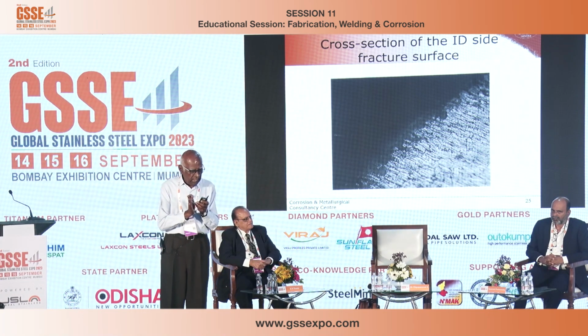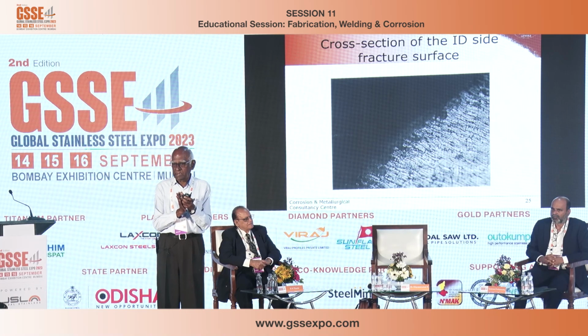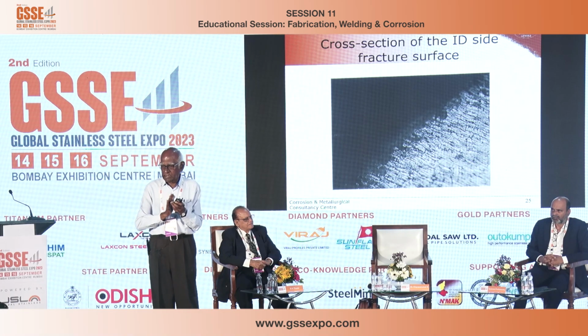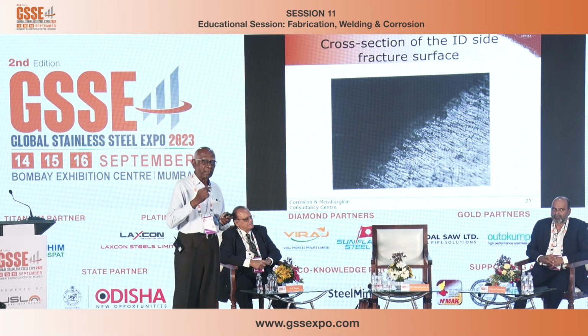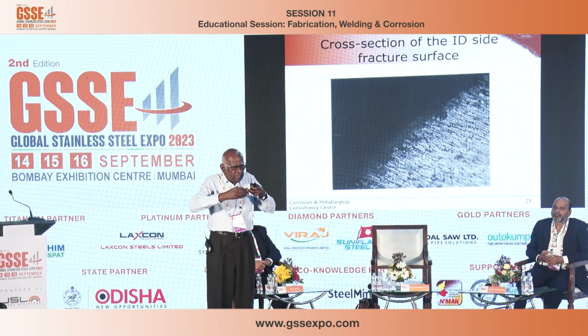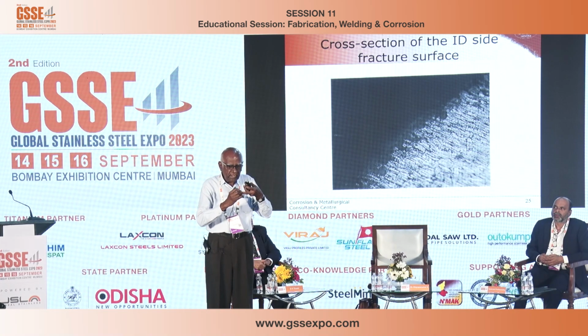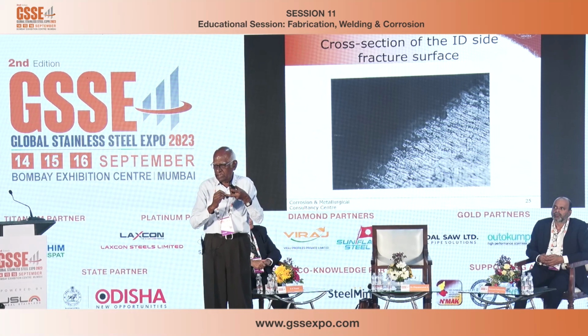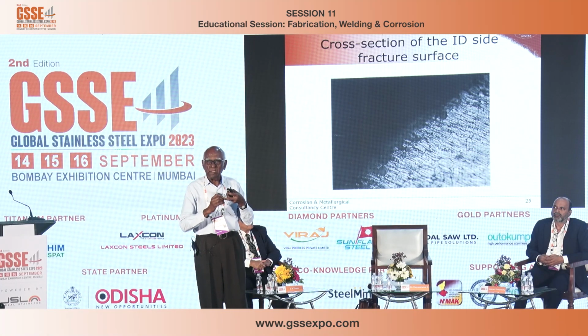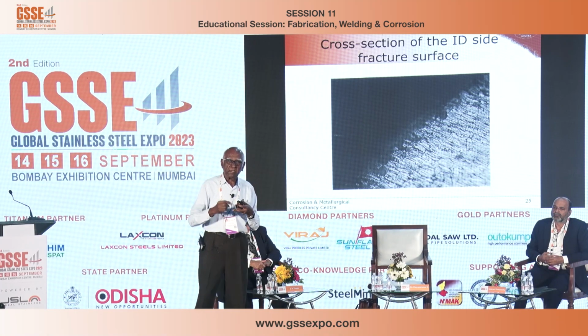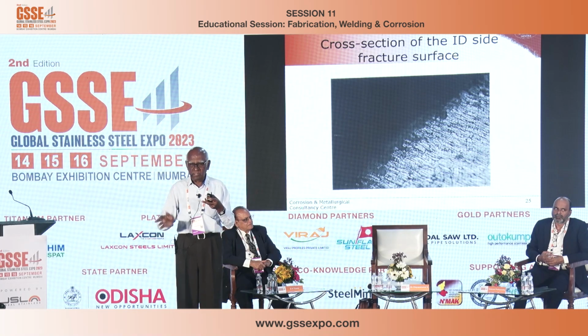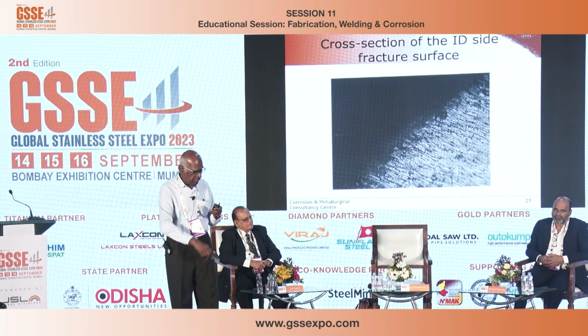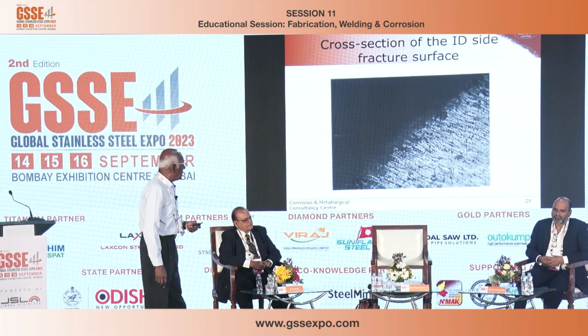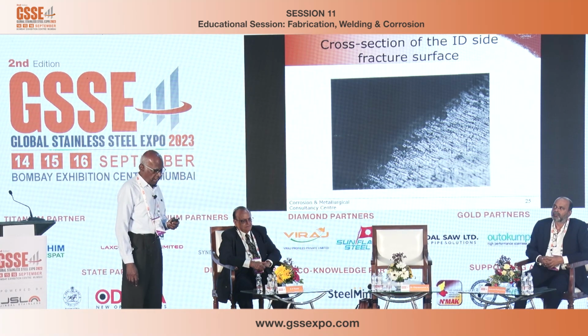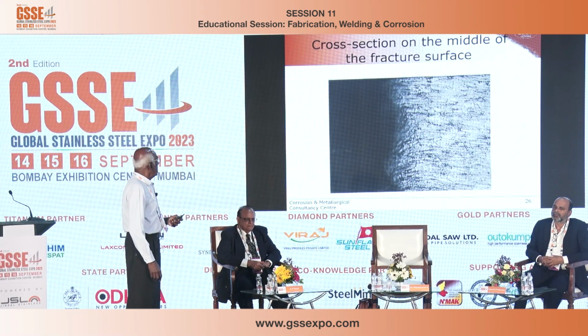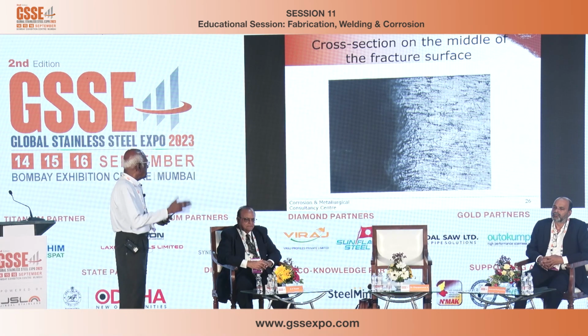So the weld is not properly matching with the parent metal. There are gaps. The gaps we call crevice. If you keep your fingers very tight, the air gap is called a crevice. When there is a crevice, solution can go inside and start eating away the parent metal. So crevice corrosion has happened here, and that is the cross section of the ID and the cross section of the middle of the fracture surface.